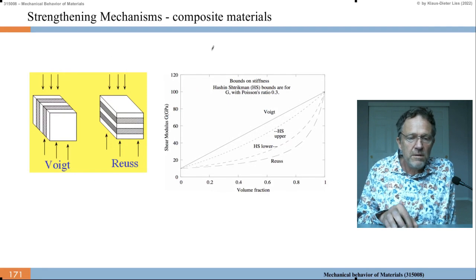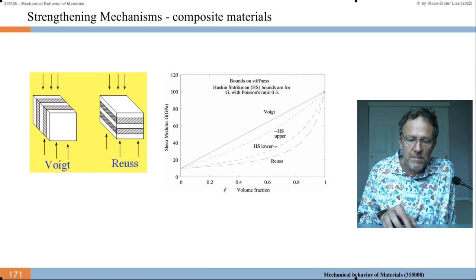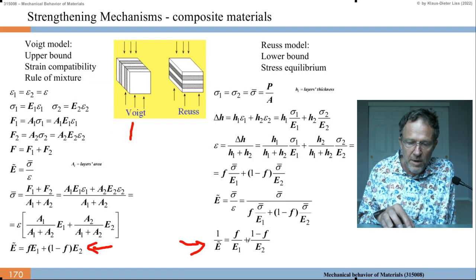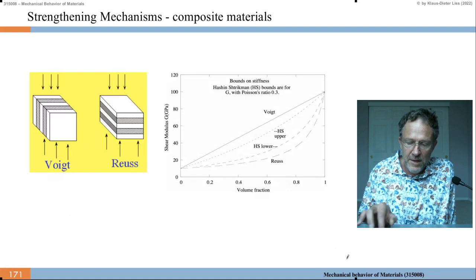If we look at the strengthening mechanisms of composite materials, then this is the Voigt behavior. In the Voigt behavior we have the volume fraction and the shear modulus here. Volume fraction is F. So Voigt is here. It's just a linear behavior. So E is linear in the volume fraction. And here E is related to the reciprocals. So if you solve it for E, then it becomes this model. The Reuss model is compared to the Voigt model.